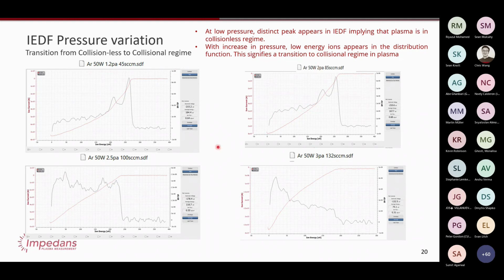And then just going to 2.5, this peak structure is almost completely lost. And now you have ions, the energy is evenly spread over everything from 0 to twice the maximum energy. And then just going to 3 pascal, just half a pascal up, now ions are mostly low energy and a lot fewer are high energy.